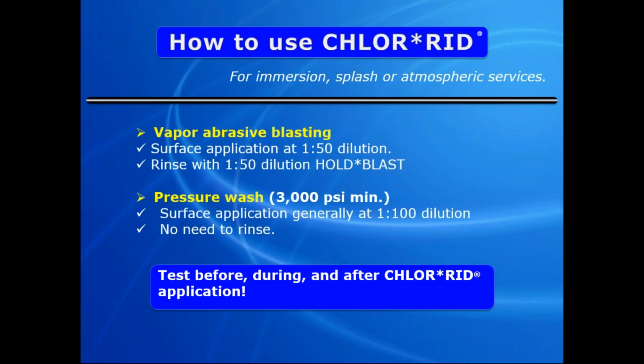We talked about tests before, during, and after Chlorid application. The reason we say during the Chlorid application is because we don't want you to test before and test after, and then all of a sudden say, wait a minute, it hasn't met specifications, so you have to go back and redo the whole job. We don't want you to do that. What we want you to do is test, find out where your problem areas are, and then have your applicator apply the Chlorid at, say, a 25 square foot surface area. Let it dry, blow it dry, and then come back and test in those areas where you found the high concentration, and just make sure that the applicator is doing the job well enough